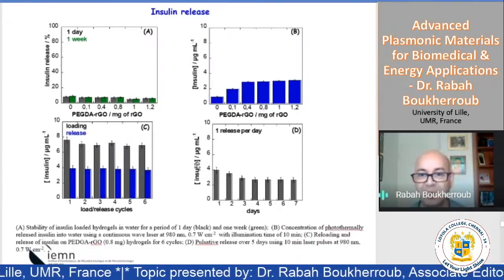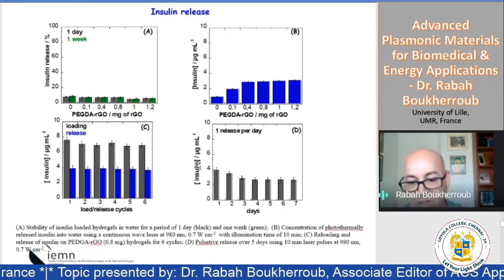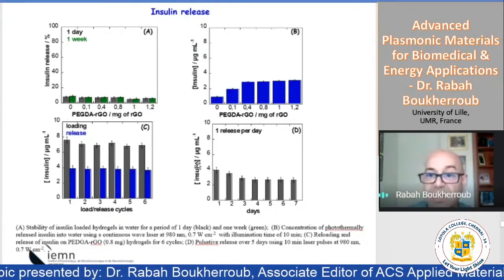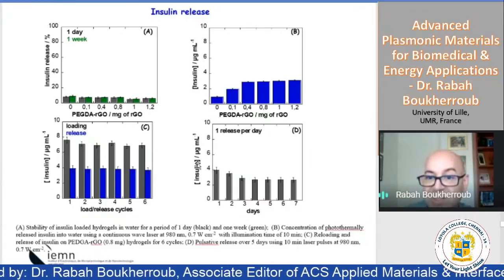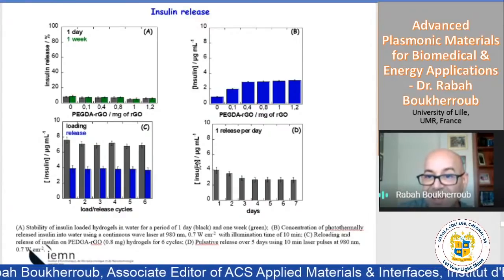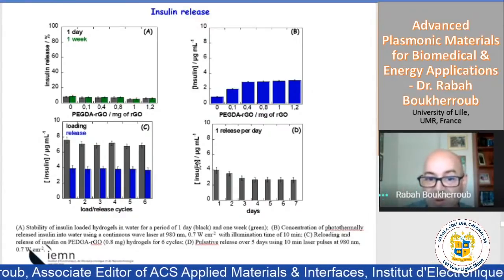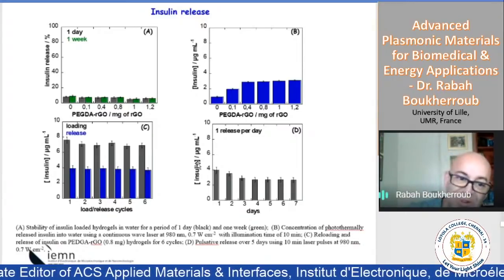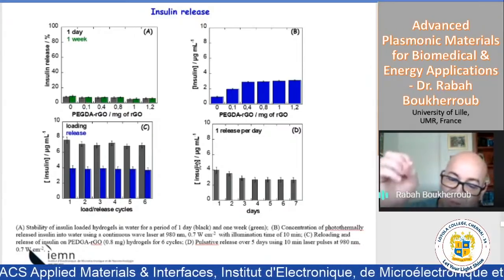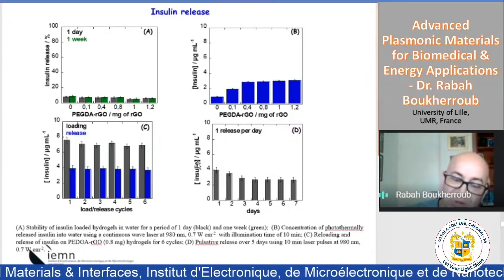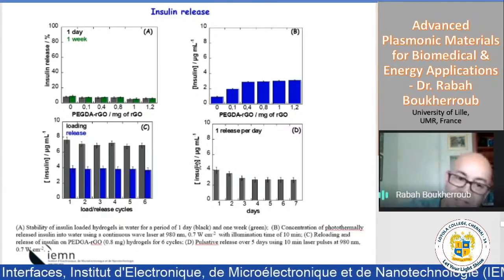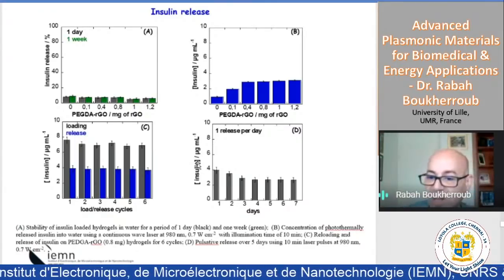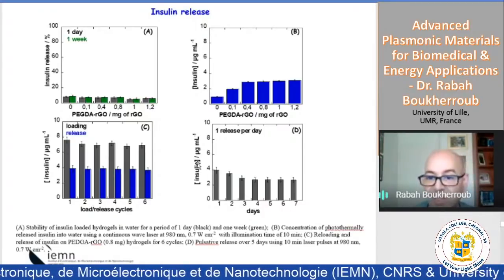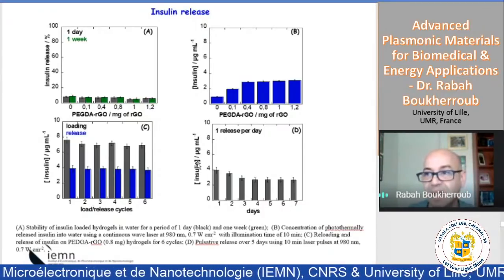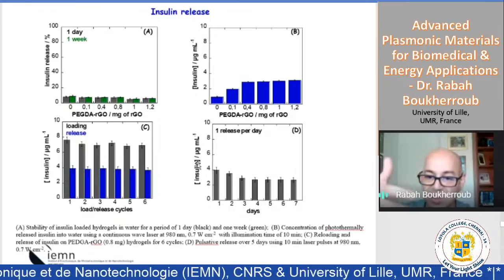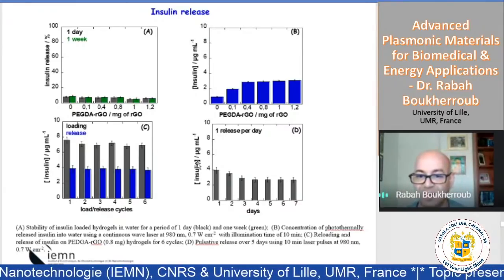What's important now is, imagine that you have a molecule inside this hydrogel but you cannot release it. That's problematic, because if you cannot release it, it's stuck in the hydrogel and you cannot make use of it. That's fortunately not the case. When I expose this to the light, I can easily release the insulin. I can load it again and release. I can reuse it, which means I can use it over days and days. I can really store insulin and release it when I want, just when I turn on the light.